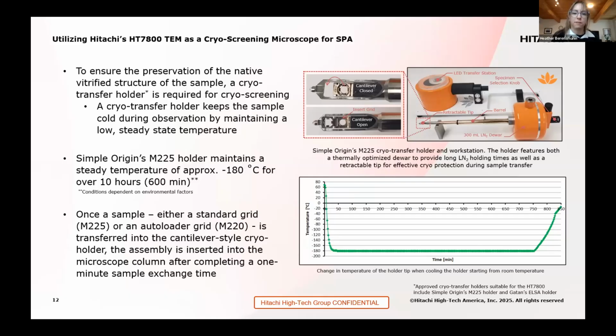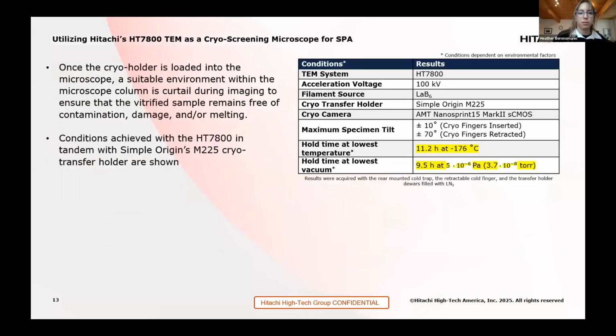This holder has two different variants. We're able to observe either regular standard 3 mm grids, or we can also load in autoloader grids, if you're familiar with Thermo Fisher scopes. Once we load the sample into the transfer holder using this cantilever design, we can take the entire holder and put it into the microscope, where it can undergo a 1-minute sample exchange time. So very quick and easy throughput to get a holder into the microscope column in a minute and get ready for cryo screening applications.